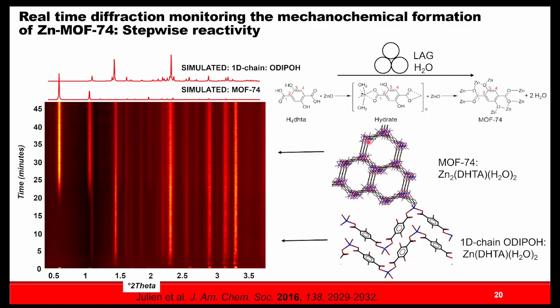One of these is for the synthesis of metal organic frameworks. So in this case, this was some early work I did in 2016. We're taking dihydroxy terephthalic acid, which is a MOF linker, with zinc oxide. You mill the two together and you basically get MOF-74, which is a nice coordination polymer. It's a nice MOF, has hexagonal channels, really beautiful structure. And you get 2 waters as your byproduct.